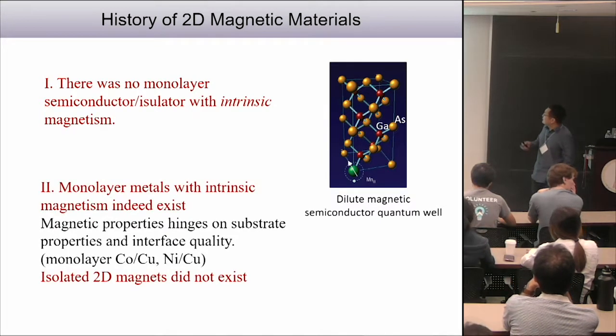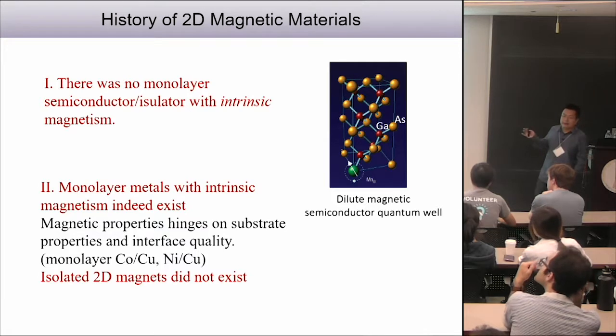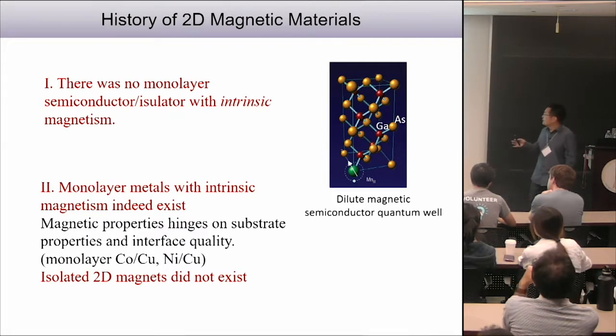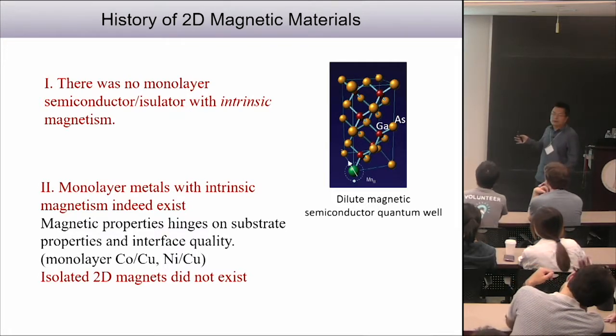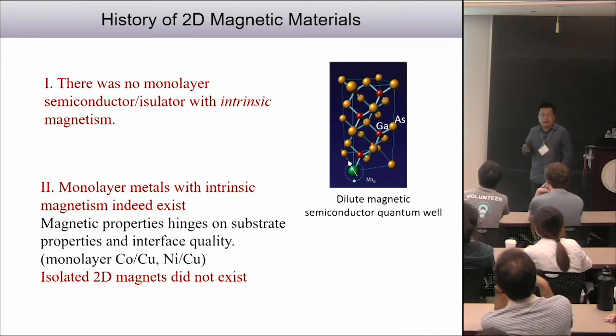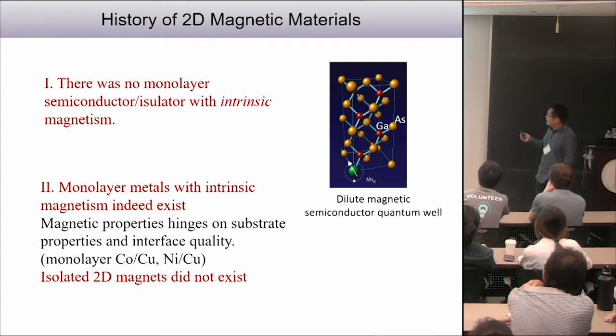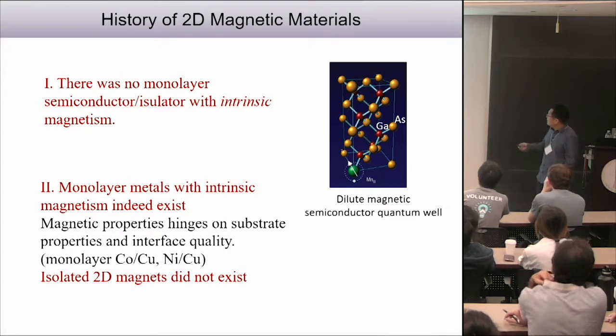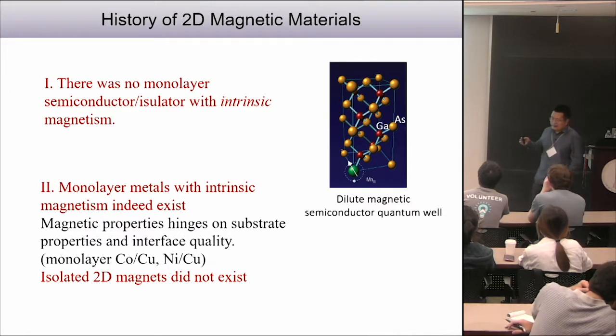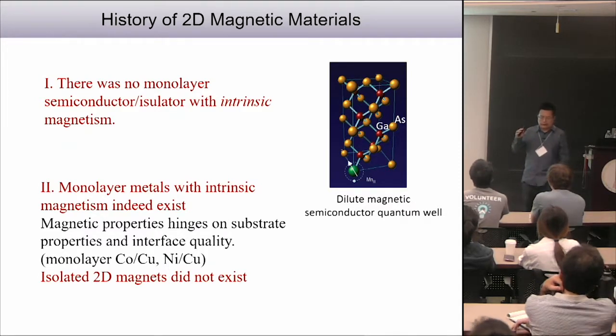The second is, well, monolayer metals with intrinsic magnetism indeed exist. For example, like monolayer cobalt on copper and monolayer nickel on copper. But the copper substrate is quite important actually. Therefore, isolated 2D magnets actually did not exist. The challenge, as I see it, is that in the past when you try to get these